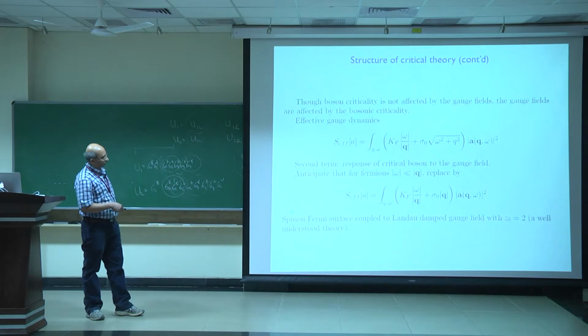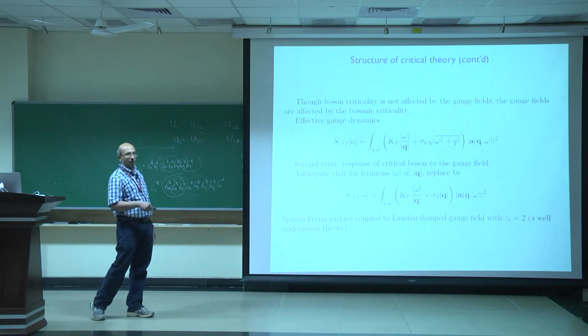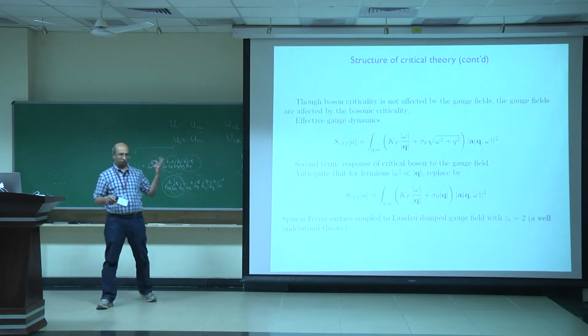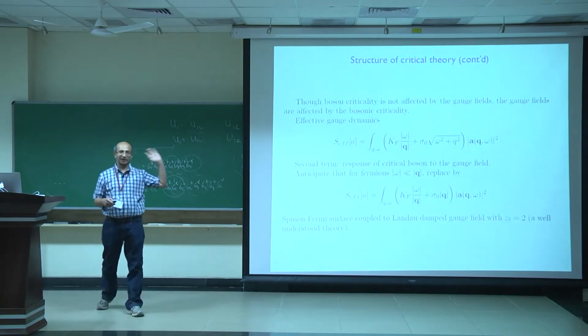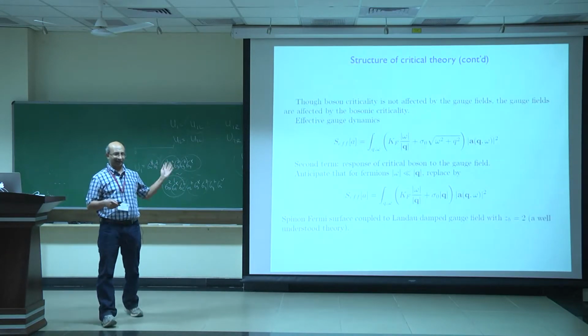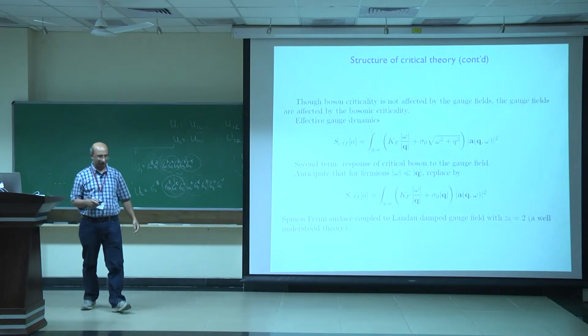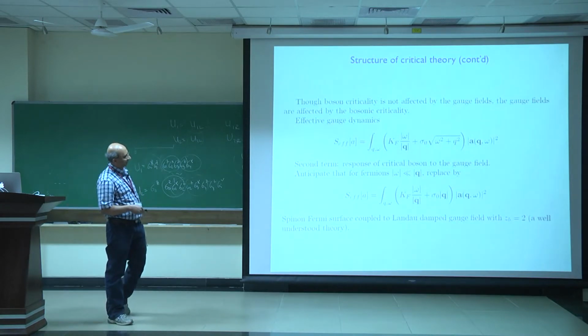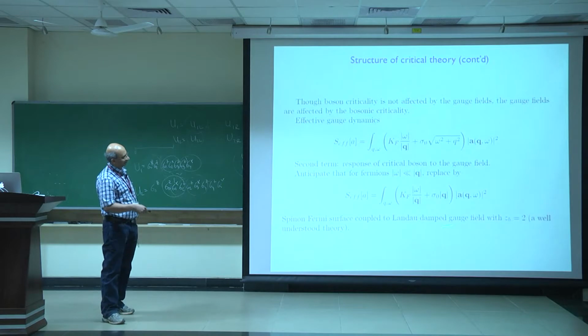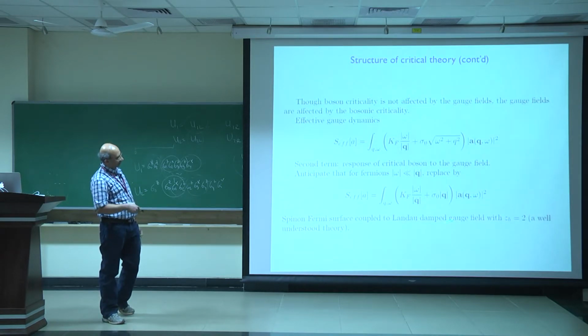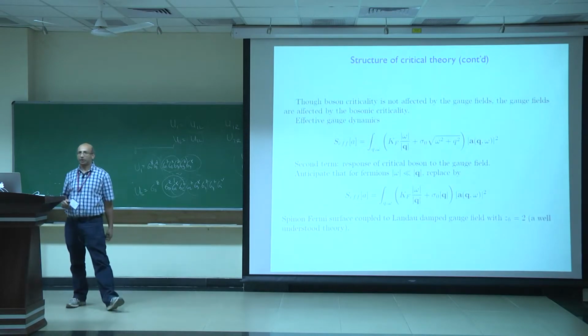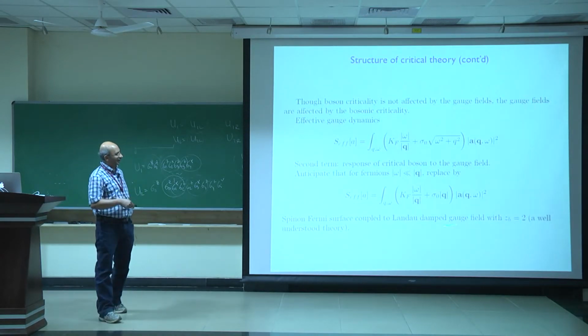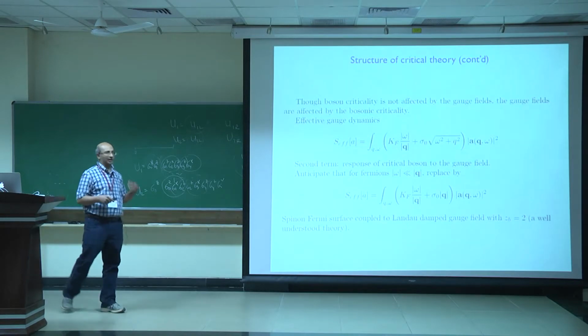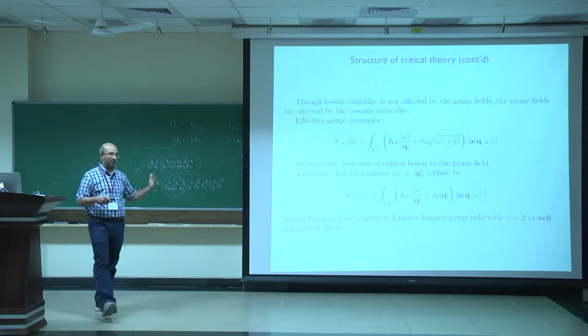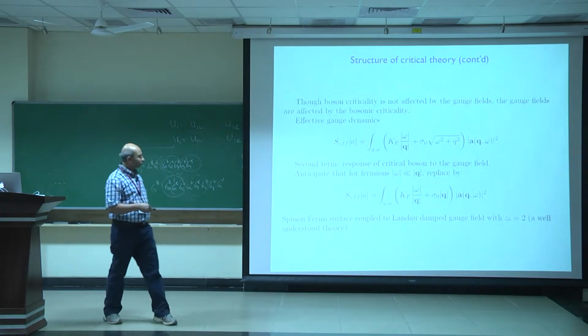Now it turns out, so the spinon Fermi surface is coupled to such a gauge field. And these problems of Fermi surface coupled to a gauge field have been discussed in the literature for a long, long time. There are still ongoing discussions, but one limit in which the problem is actually understood is when the gauge field has precisely this dynamical exponent equal to 2 dynamics. Okay? This turns out to be a tractable case where the coupling to the gauge field only introduces marginal deviations from Fermi liquid behavior. Okay?